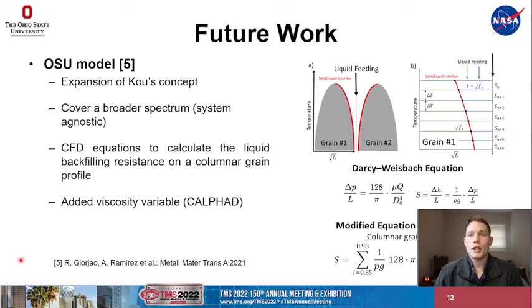In order to develop this model, we use computational fluid dynamics in order to calculate the liquid backfilling resistance on a columnar grain profile. So in figure A, you can see two grains shown that are growing side by side. In order for these to solidify, liquid has to feed down into the space between the grains, and the resistance of the liquid to flowing down into the grains can relate to solidification cracking. So we added a viscosity variable as well as some other factors from CALPHAD into this equation, which is shown on the bottom right, that we have developed in order to estimate this solidification cracking susceptibility.